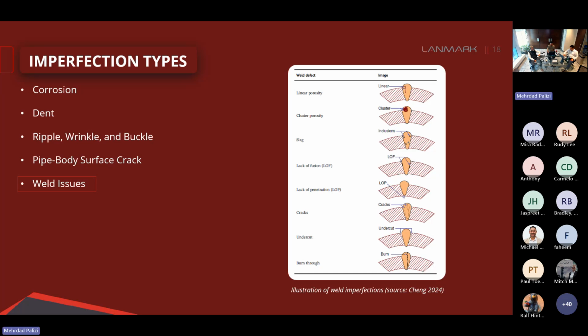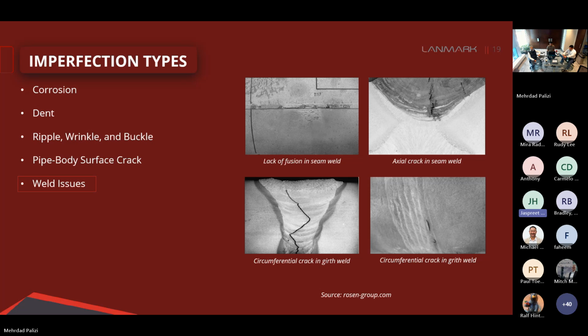And finally, one other category is weld imperfections over seam and girth welds. So here we might have planar flaws such as cracks, undercutting, or lack of fusion. They could also be volumetric flaws like cluster porosity, slag inclusion, or lack of penetration. Weld areas are more susceptible in comparison with the pipe body.